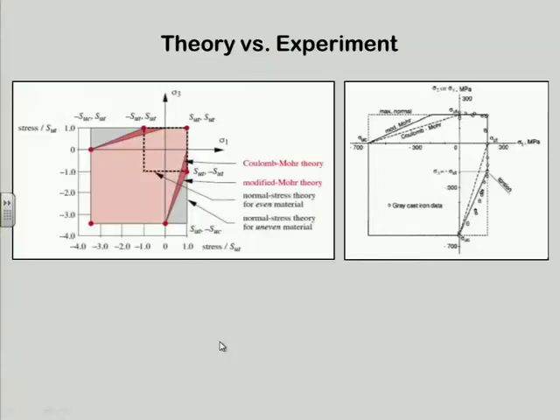We need to look at the test data. If you look at the right panel here, you see little dots which are where the parts failed under different combinations of stress. So somebody gave it a sigma 1 of that amount and a sigma 3 of that amount, and it broke there. And another one broke at a sigma 1 of that amount and a sigma 3 of that amount, et cetera. So you can see that they're fairly close to that little square corner up there, and they're okay down to minus SUT.